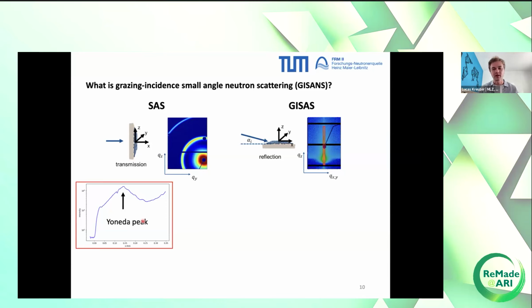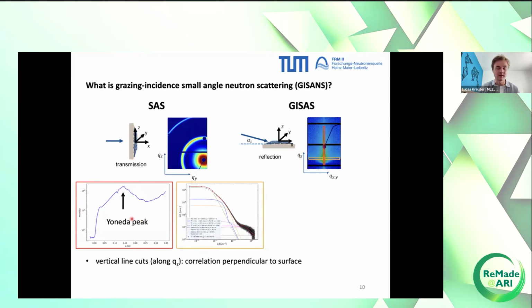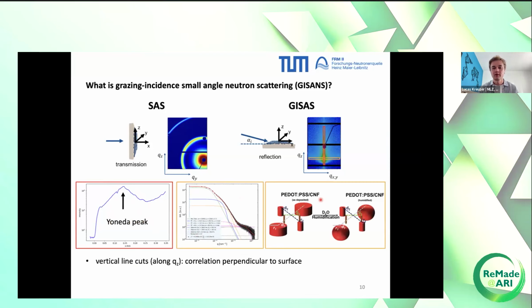And then what you can do is, for example, a horizontal line cut at this Yoneda position, because there you have a lot of signal, which would look like this. And this you can then fit with certain structure factors, form factors, which give you information about the size, the shape, and the distance of characteristic periodically appearing features in your film.